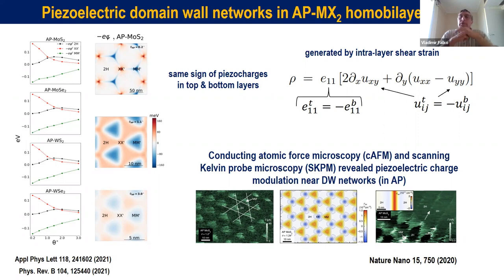Now, what happens in the antiparallel orientation of the unit cells of the two crystals is that there is a cancellation of two minuses, producing the same charge accumulated in both layers on top of each other. The reason is that the deformations the crystals need to develop to bring their lattices together have opposite signs, and therefore produce opposite signs of strain tensors at the same places in the geometric Moiré pattern. But at the same time, the two unit cells of the two crystals are inverted, and therefore the material constants of piezoelectricity are also of the opposite sign. Those two minuses cancel, and then we get modulation of charge, which produces modulation of electrostatic potential of the same sign in both layers.